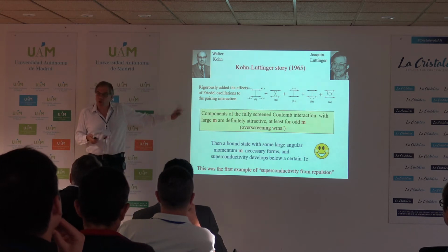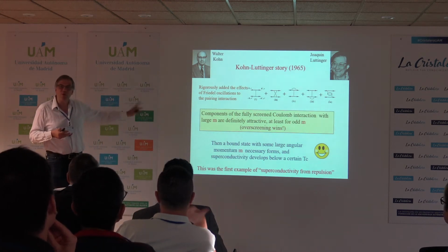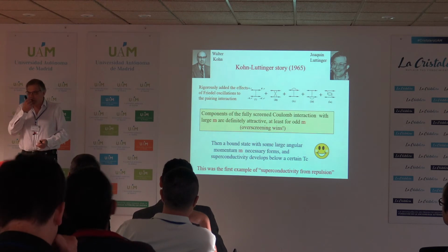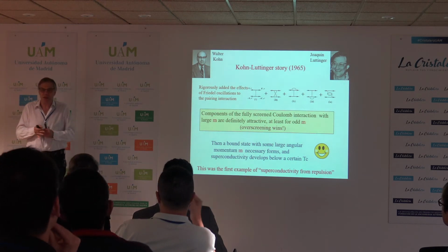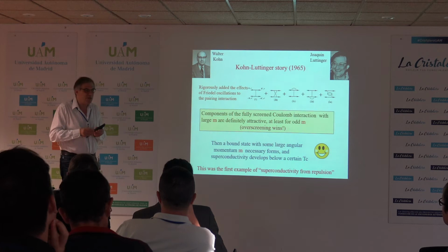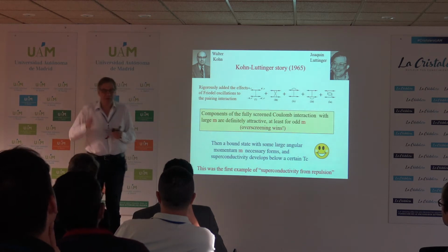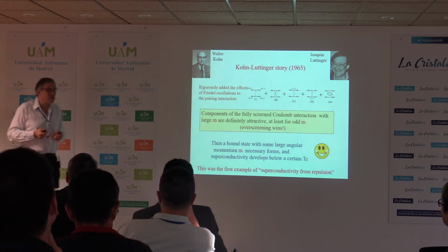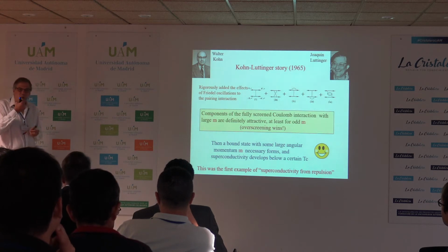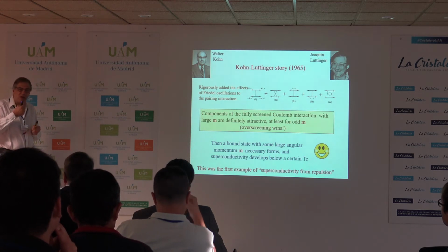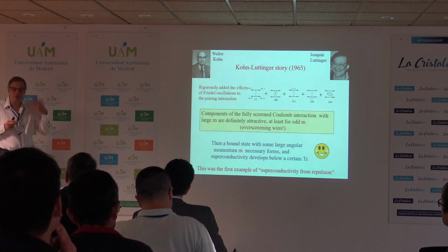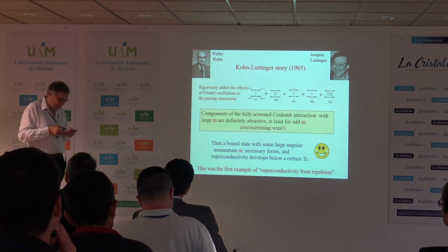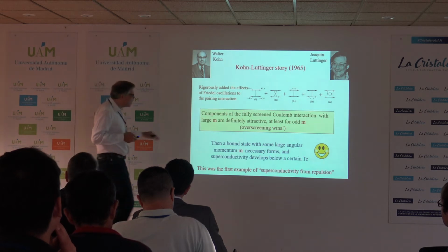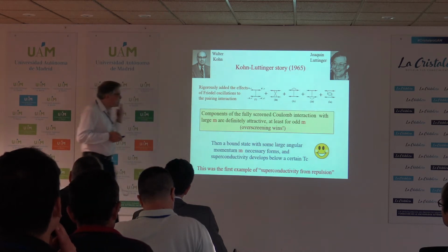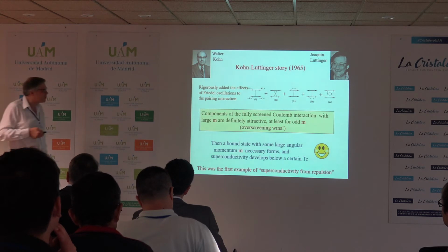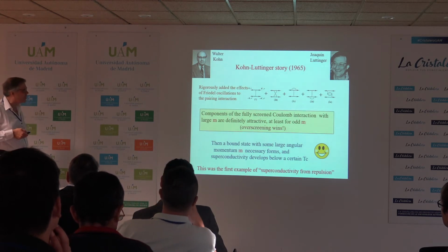This was considered a joke at that time because there was a story associated with that paper. They were too honest to give an estimate for Tc and got Tc of about 10 to the minus 20 Kelvin, which was zero by all accounts. It turns out later that they were applying the results to angular momentum L equal to 2, while if you take their results and apply them to angular momentum L equal to 1, you will get 10 to the minus 3 Kelvin, which would be similar to the Tc for superfluidity in helium 3.